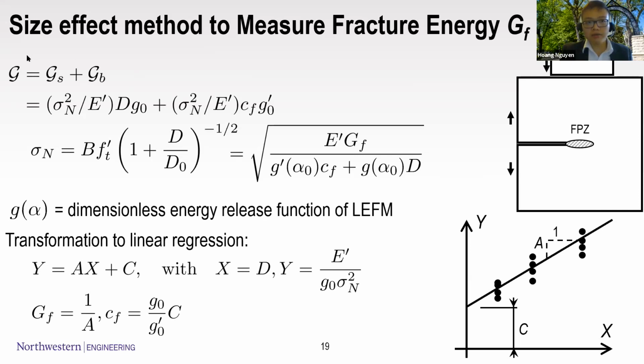So you can break the energy of the materials into the part that will be released, and what will change with the size, which is the elastic part starting here, and then the energy that is dissipated within this zone. You can see that does not depend on D. After manipulating to get sigma_n, the nominal strength, which in most cases is just defined by the maximum load that you can measure over the thickness and the characteristic length, you can obtain the relation between the nominal strength and the size of the structure you measure.